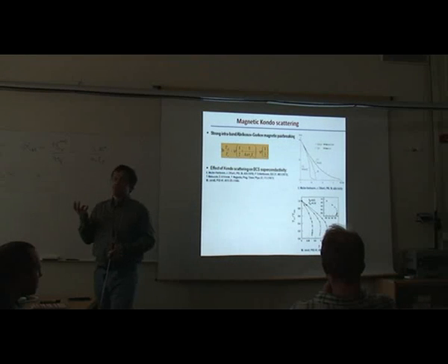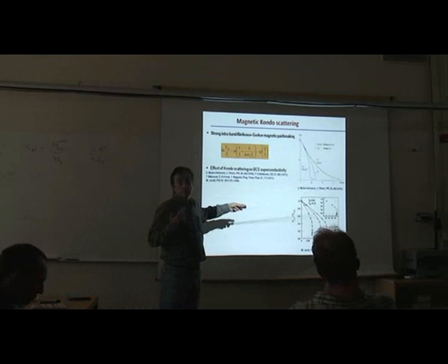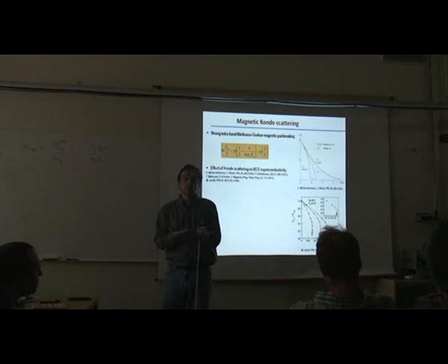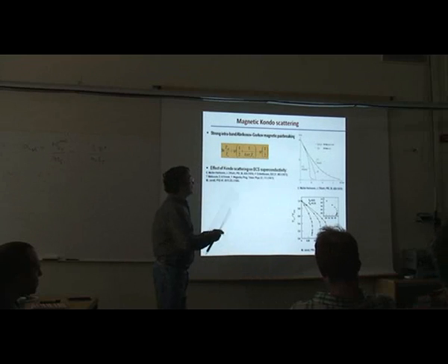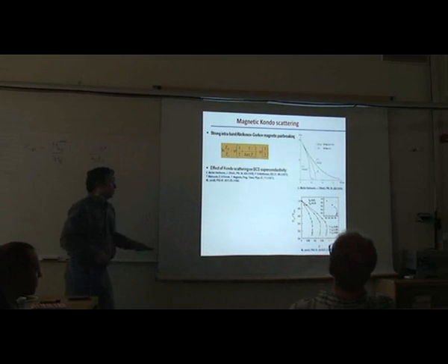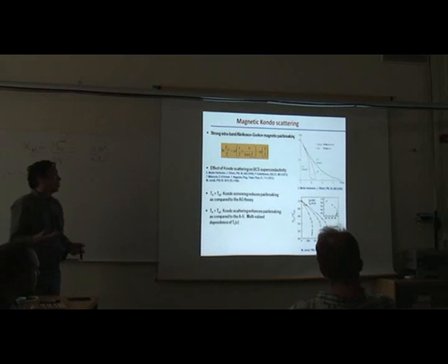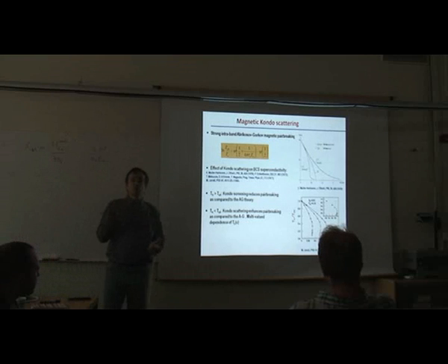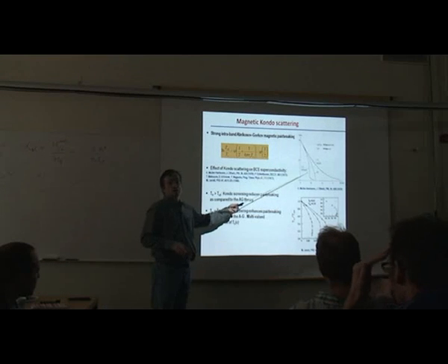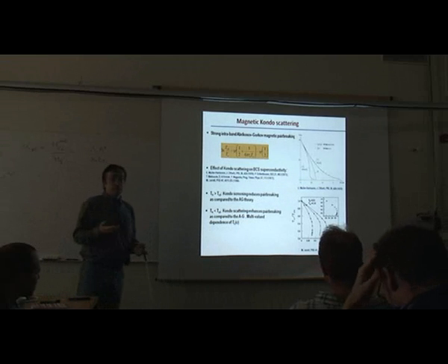However, if the Kondo temperature is smaller than Tc, we have exactly the opposite. Tc drops faster than the Born approximation, simply because the Kondo scattering increases as we reduce temperature. The scattering amplitude grows logarithmically. So this is this curve here. So this is all for single band superconductor. And it's actually been seen experimentally. So this is well understood. So here is our puzzle. In our case, the Kondo temperature is smaller than 2 Kelvin. And our Tc is 40 Kelvin. So we're supposed to be here. So we would expect much stronger pair breaking effect by magnetic impurities. Instead, we see something completely different.